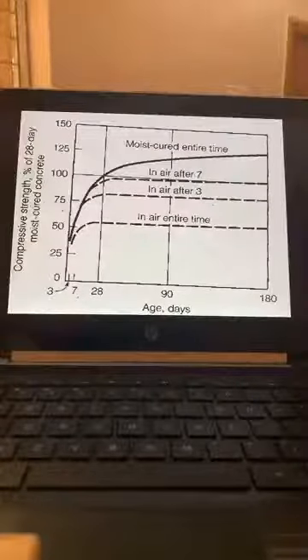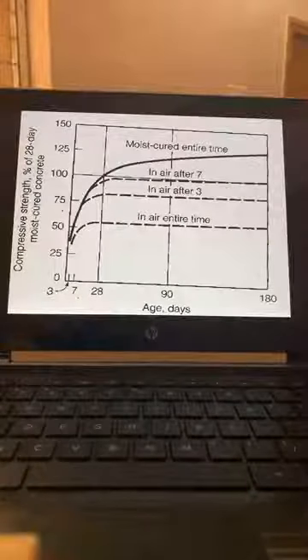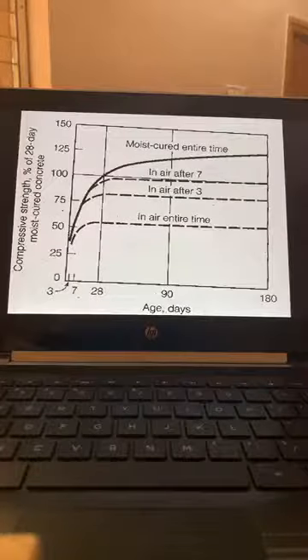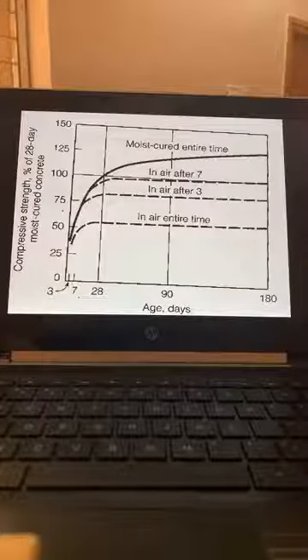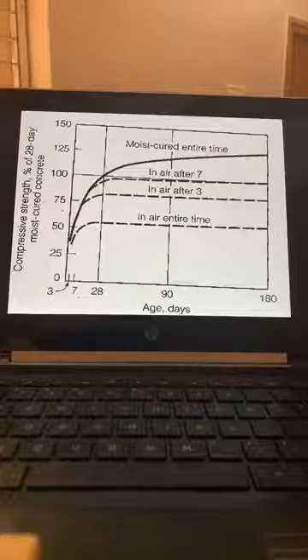100% strength is achieved at 28 days as shown in the graph — a very good representation. Membrane curing: concrete has water in it that we have added as wet concrete. The membrane coating — like on the metro rail piers in Hyderabad — is applied within six hours after concreting so that the membrane will not allow evaporation to take place and moisture is maintained.